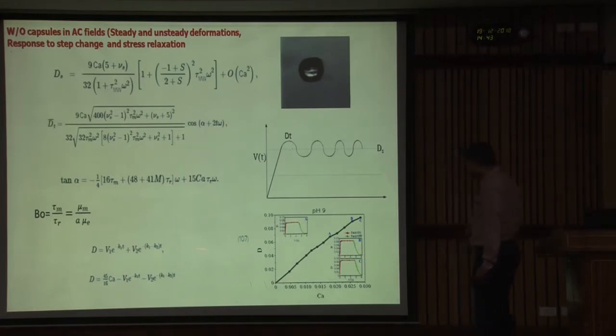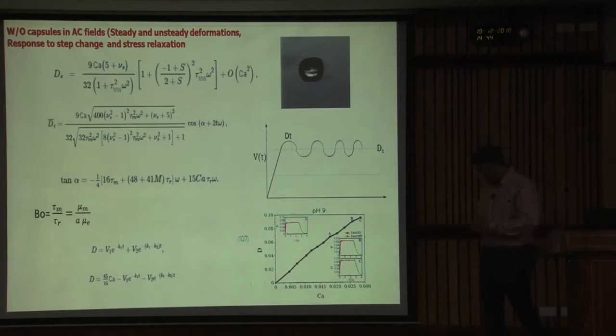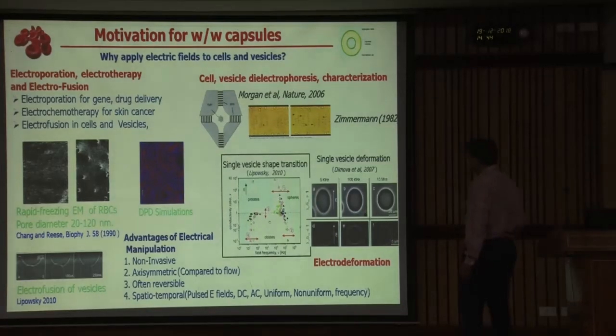We also have expressions now for a viscoelastic membrane which is subjected to startup or relaxation. If one experimentally gets these curves, one can fit these expressions and get the membrane viscosities and elasticity. Okay. So this is what I have to say about the water in oil capsules. I'll now move on to water capsules.